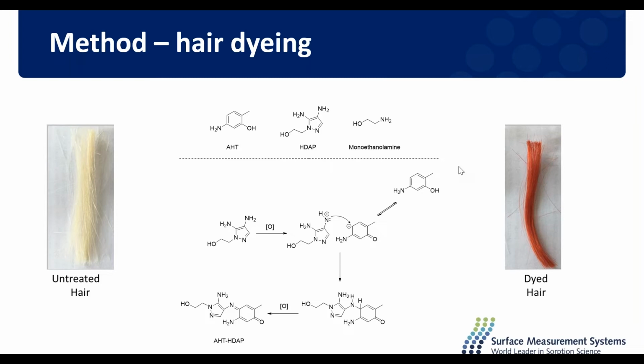And we chose this red dye, this AHT HDAP dye, as it's quite a simple dimer which forms in the hair. It's an oxidative reaction in the hair, and it's not a reactive dye, so it doesn't interact too strongly with the hair fibre, which is what we were looking for.